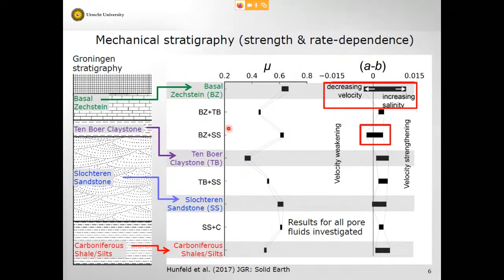And he basically found something like this. This shows friction coefficient of all of these different lithologies and their mixtures. And this shows the rate dependence. This is a measure of the potential for accelerating seismic slip. Okay, so if this is negative, then slip can accelerate and you can get an earthquake developed. If it's positive, you do not expect that to happen.